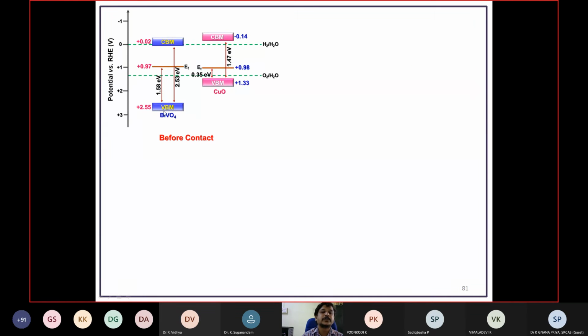So here you can see the bismuth vanadate showed a conduction band minimum closer to the hydrogen evolution potential, and it is below the oxygen evolution potential. Then if you look at the copper oxide, the copper oxide showed a conduction band minimum above the hydrogen evolution potential.